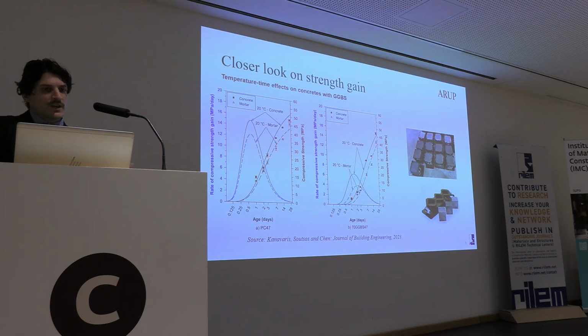And we've had a closer look at strength gains. Normally when you look at strength gain, you look into casting mortar specimens instead of concrete specimens because of logistical issues or even cost issues, because mortar specimens are smaller. But we found, for example, that there are some discrepancies between the strength development of mortar and concrete specimens, particularly on the strength gain rate.